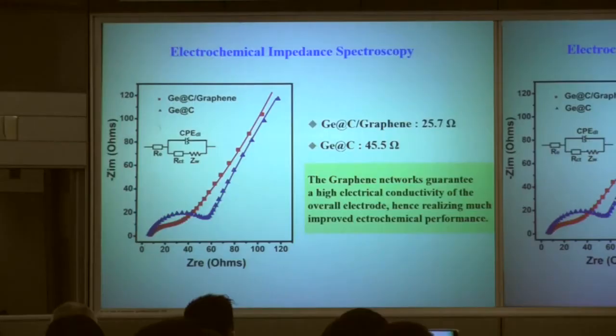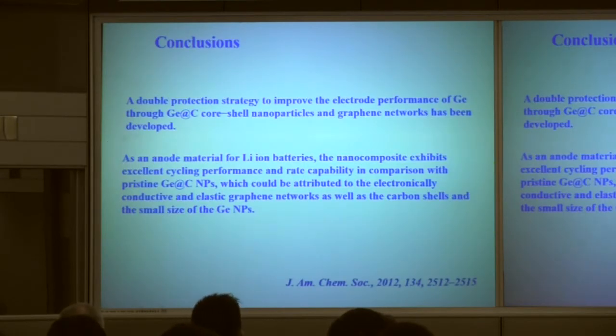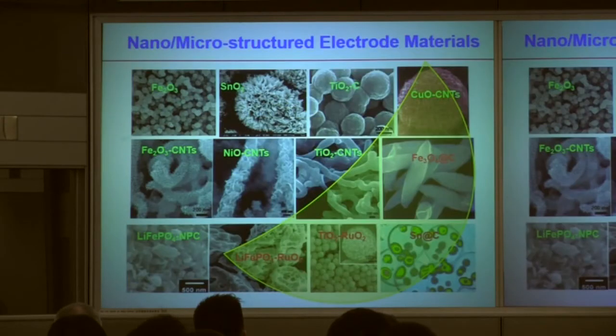Here is the electrochemical impedance spectroscopy. That means after this treatment, the conductivity of this nano-micro composite material becomes much better than pure germanium material. And here is the conclusion. And we also prepared other nano-microstructure electrode materials. You can see a lot of these. And we measured the electrochemical property. We found some of them are very good, very useful for lithium-ion